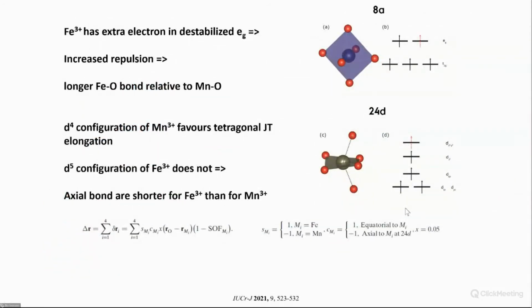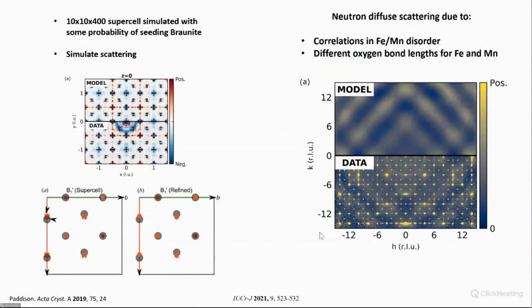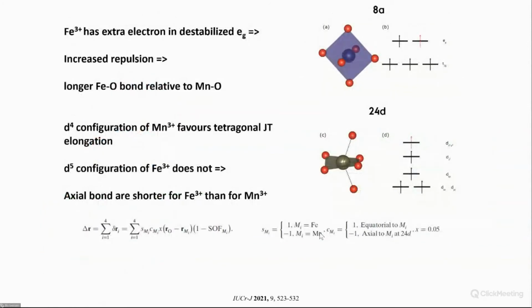And here my link is to the chemical bonding again, because if you have a very octahedral site, then iron 3+ of course has an extra electron compared to the manganese. So there's an extra electron in the antibonding orbital, and this is destabilized, so I expect the iron-oxygen bond to be longer than the manganese-oxygen. If you take the highly distorted site here, then you will tend to have a Jahn-Teller distortion for the manganese, but not for the iron 3+. So here the actual bond is probably longer for the manganese, whereas the ones in the planes are the same. So one can say, okay, now I sit on my oxygen, what are my metal bond lengths, make these coefficients and try to refine them, and then you get exactly this diffuse scattering as seen before. So this is the chemical bonding that basically drives the diffuse scattering.